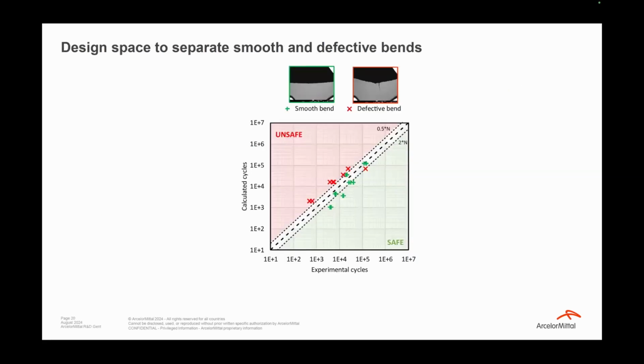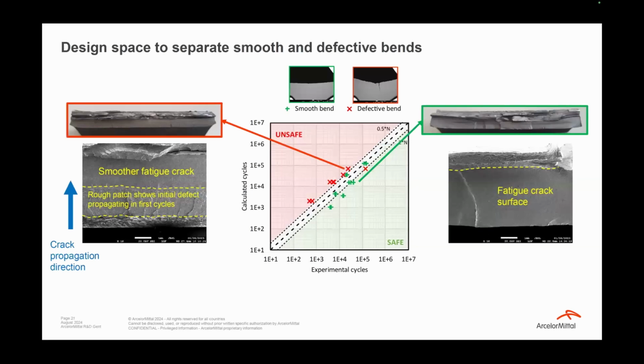And if I do the same with, not with the bending ratio, but smooth bends and defective bends, now the use of the unsafe and safe regions are more clear. And if I just check how these cracks look like, so the crack propagation direction is always from top to the bottom. So, yeah, here you see the material behind, so you should just ignore this part. What we see with the defective bends are, first, there's a rough patch, shows the initial defect propagating in the first cycles. And we can even hear that in the test. Once we start the test, there's this click, but the load is not that high, so it's still that the material can collect itself, and then you can get smoother fatigue crack.